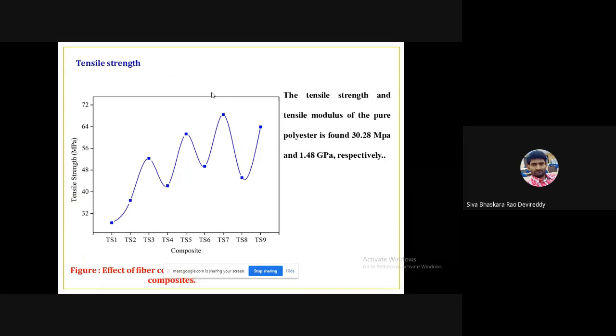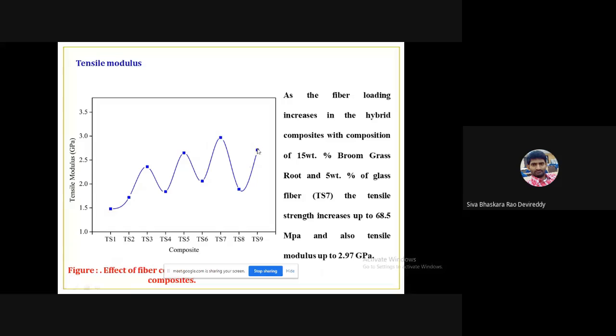Tensile strength of the composite. Here in the tensile test, we calculated the tensile modulus and tensile strength. Initially, the neat polyester has a tensile strength of 30.28 MPa and a tensile modulus of 1.48 GPa. When we add the reinforcement phase, gradually the tensile strength and tensile modulus both increase, and the maximum tensile strength is found to be 68.5 megapascal, and the tensile modulus increases up to 2.97 GPa at 15wt.% of broom grass root and 5wt.% of glass fiber. That is the composite specimen designated TS7, which has higher tensile strength and modulus compared to the other specimens.